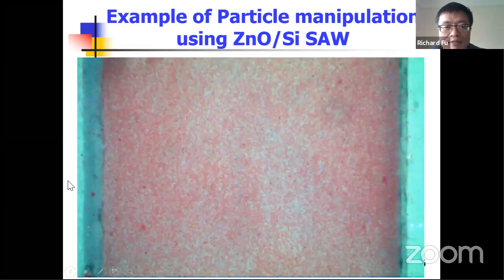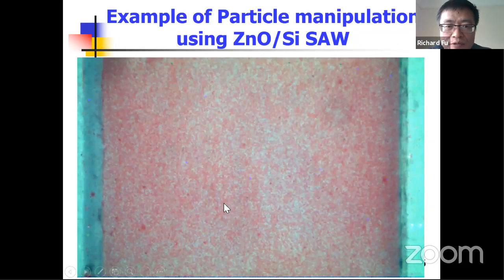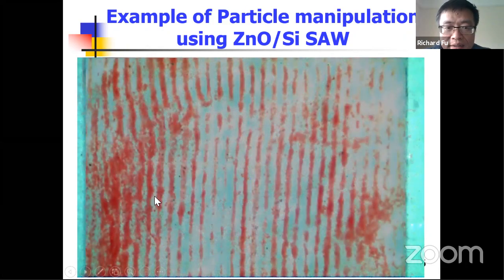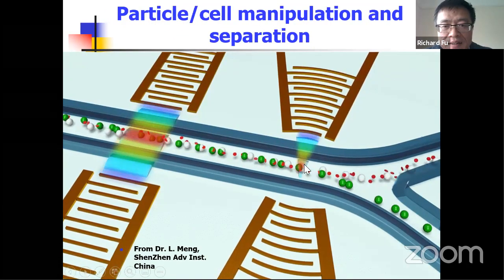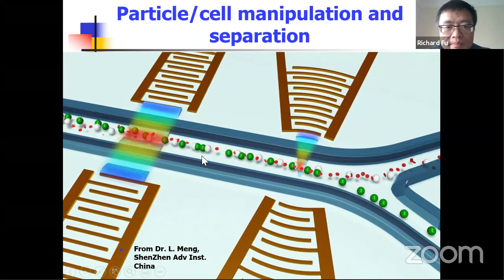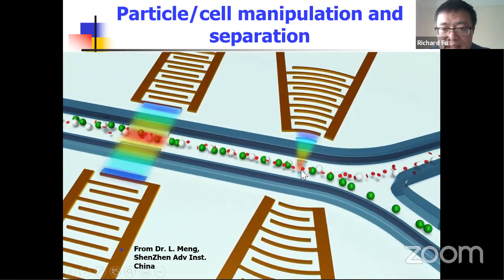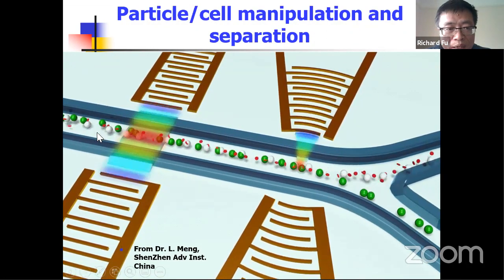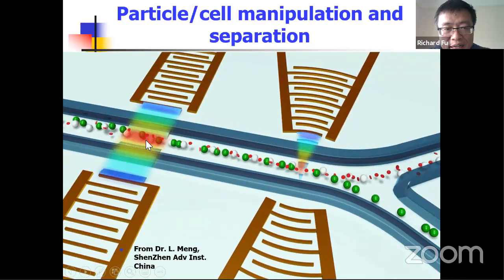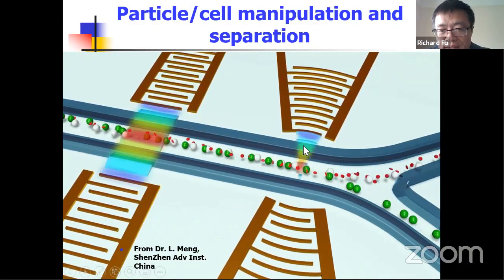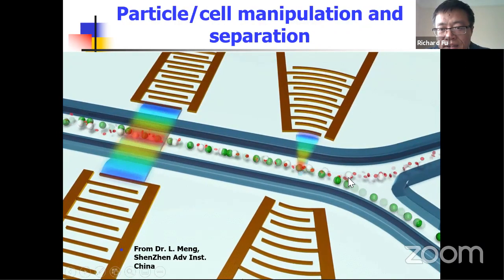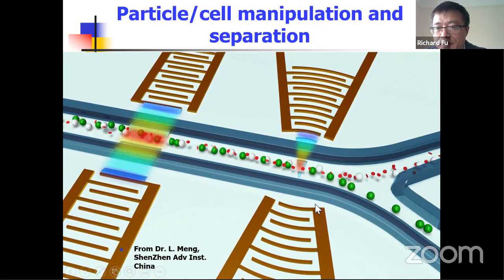So here is an example. We have a very wide microchannel. We have uniform 5 micron particles. If we apply the standing wave, they will form different lines. Of course, if you shrink the width of the microchannel, you can form one line or two lines. So the idea behind it is that we can use this for cell manipulation or separation purposes. We align all these particles using the first electrode pair, and then we can use another pair of electrodes to control it, and push different sizes of particles to different positions.